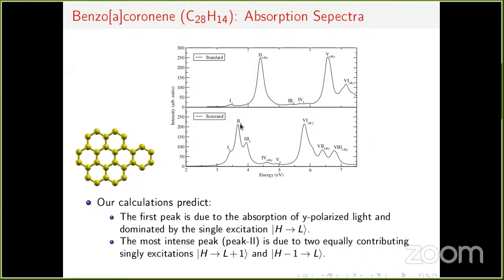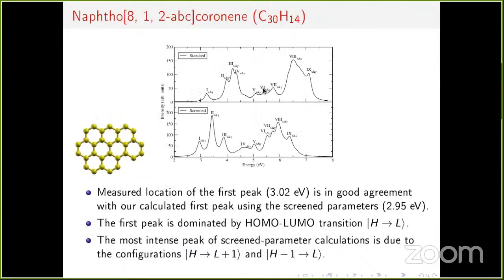The most intense peak is the second peak, due to two equally contributing excitations, H to L+1 and H-1 to L. The sixth peak for screened parameters is also quite intense, but it's not the most intense. The second peak in both sets of calculations is the most intense. And then we have also given here the optical absorption spectrum for the highly asymmetric molecule, again with the two sets of parameters.